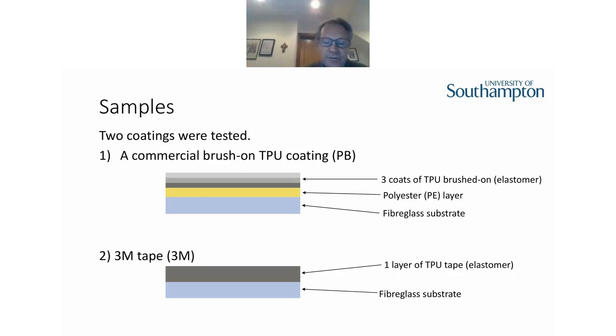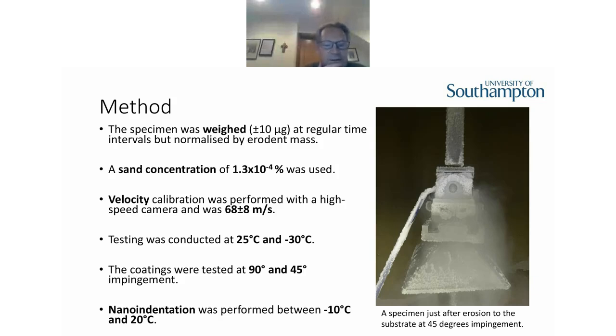It had 3 brushed layers of polyurethane, an interlayer of polyester, and then the fiberglass substrate. So quite a complicated system. So that's what we were looking at. And as you say, we tried to operate the erosion tests at ambient, so at 25 degrees, and then with the cooling system that the students deployed, we could go down to minus 30.